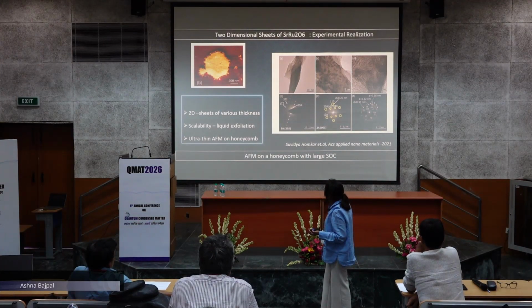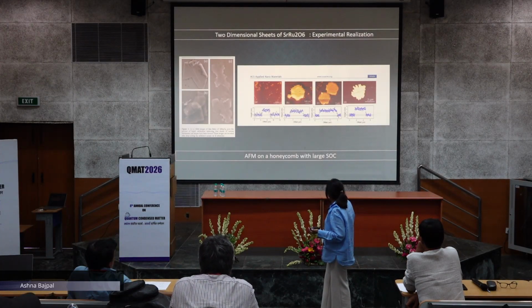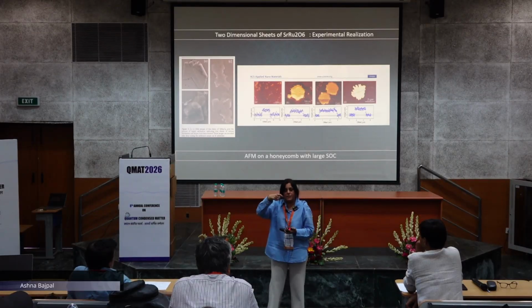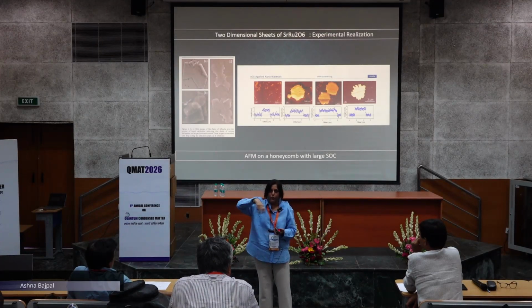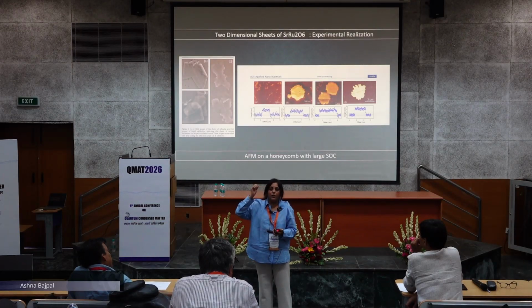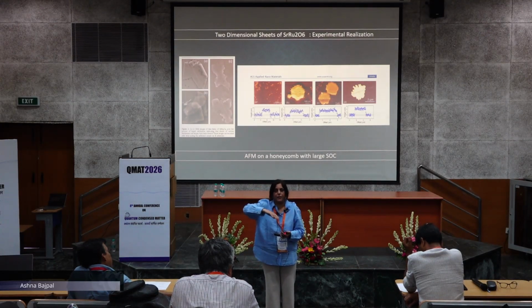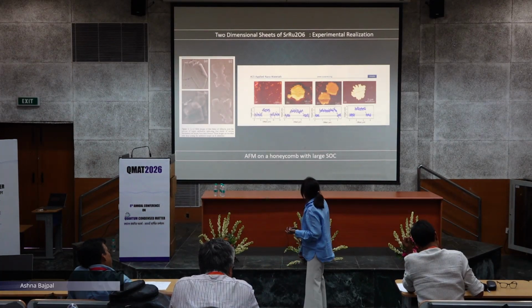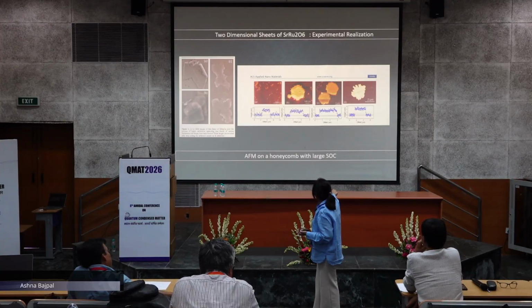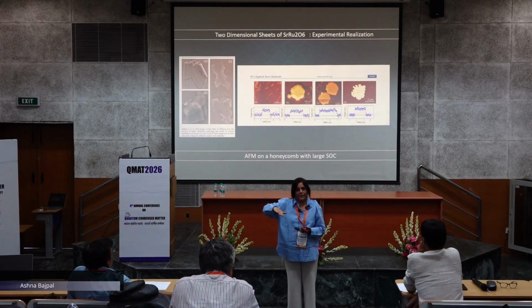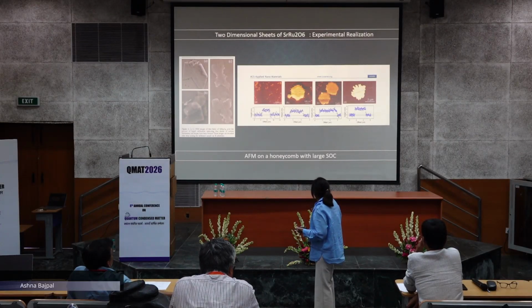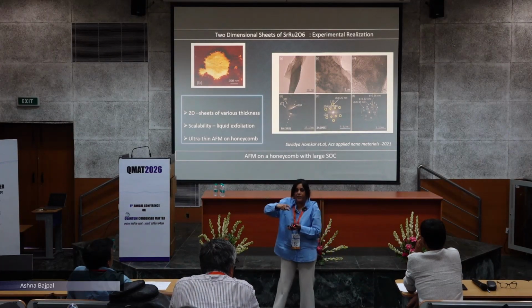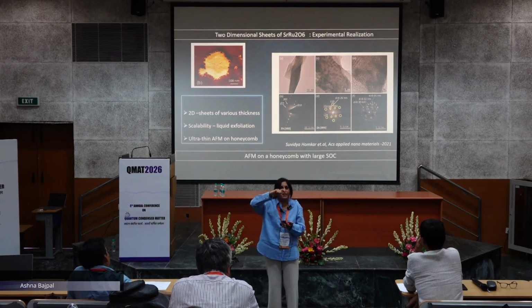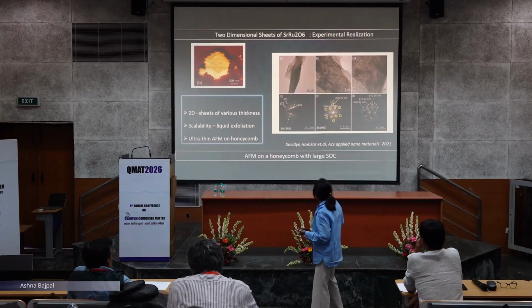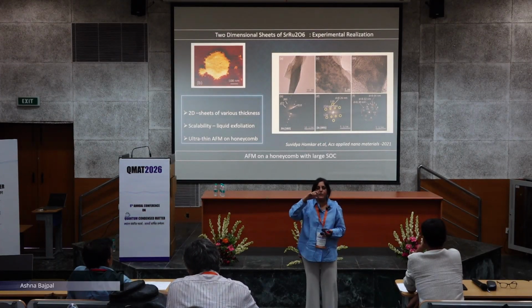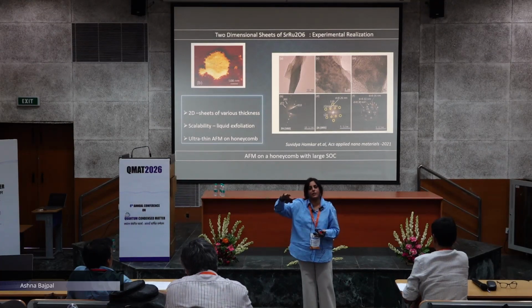Many of the sheets are exfoliated, as you can see in the first graph. Basically this is a liquid exfoliation method, and the refined sheets float in a liquid, which in this case is ethanol, and when you drop cast you get the sheets on a substrate. You get a lot of sheets in the shape of hexagon, which is cleanly exfoliated, I would say. So we found this. Now we have the opportunity to do measurements on sheets with varying thickness. This is our next goal, hopefully: to do measurements in the bulk limit and then systematically downscale to the 2D limit.